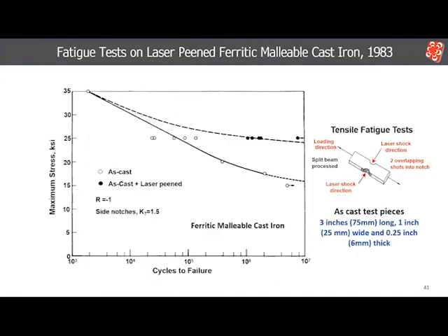To demonstrate fatigue life improvement of laser peened iron castings, tests were run on small as-cast tensile fatigue specimens laser peened into the notches on each side of the specimen as shown in the illustration on the right. The cast iron shown here is ferritic malleable cast iron. Laser peening produced a 60% increase in fatigue strength. The other types of cast iron also showed increases. After these tests, Wagner negotiated a licensing agreement with Battelle and commenced to fund the development of laser peening.